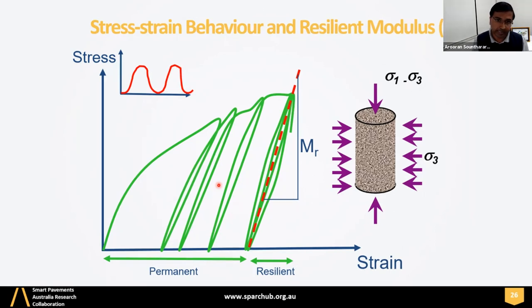At the initial number of cycles, it's going to take a certain amount of plastic deformation, which is a permanent one, cannot be recovered. And then it reaches the resilient stage, where the modulus of the pavement, in other words, the resilient modulus of the pavement, is constant. So the pavement reaches the resilient stage after the permanent deformation, and no more permanent deformation is expected for a certain time.